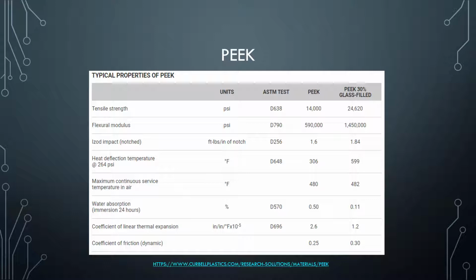Stratasys has also begun marketing a polyether ketone ketone, or PEKK, FDM filament, a close cousin of PEEK, another thermoplastic in the polyaryletherketone, or PAEK, family, under the name Antero 800NA. While PEEK materials have impressive moduli for polymers, they are also very expensive. In this case, for half a kilogram of 1.75 millimeter filament, expect to pay $325. In addition to excellent mechanical properties, PEEK is also FDA approved for use in food contact.